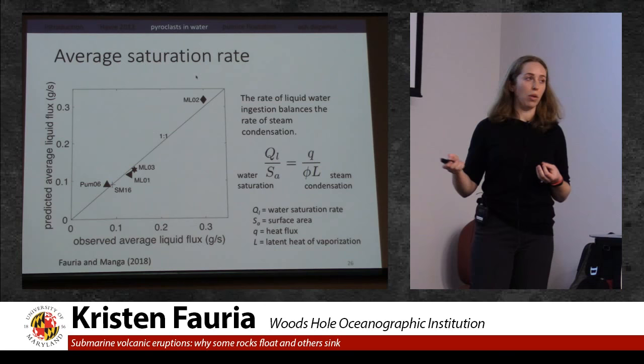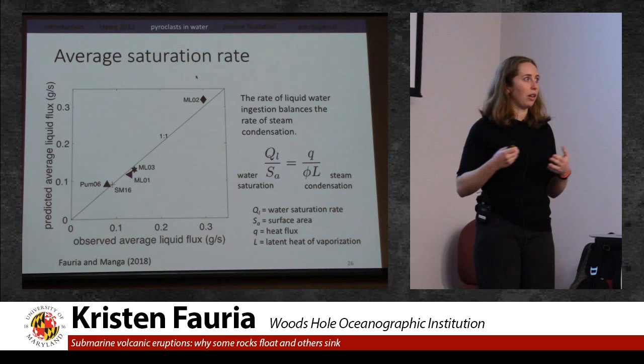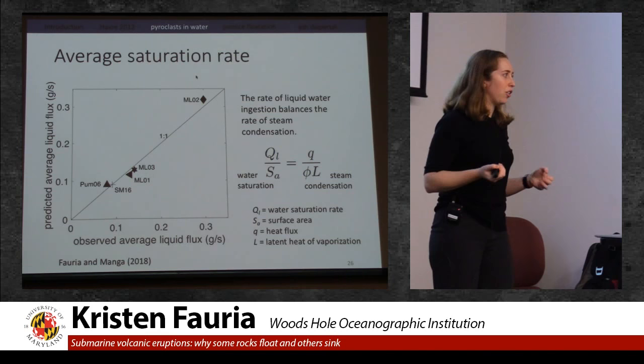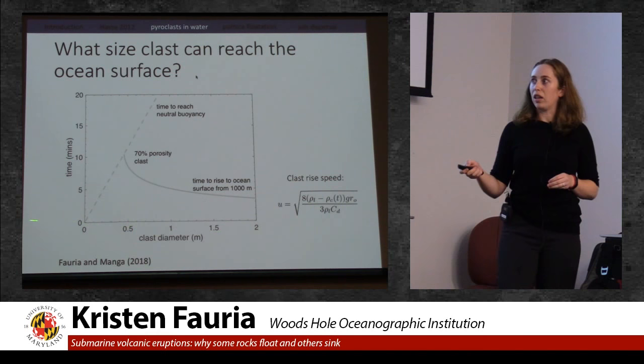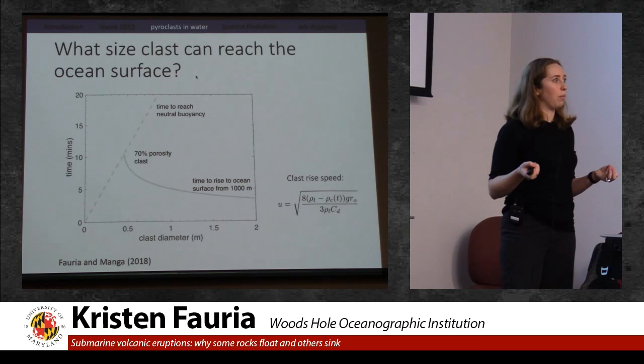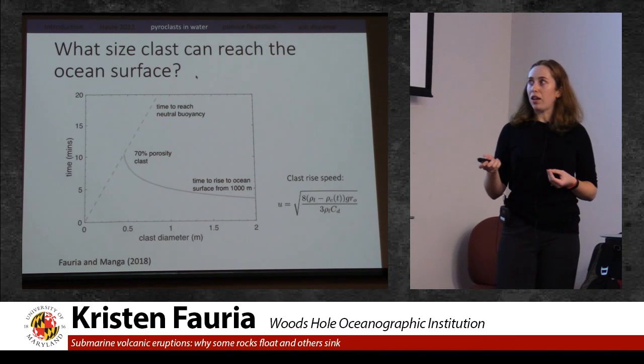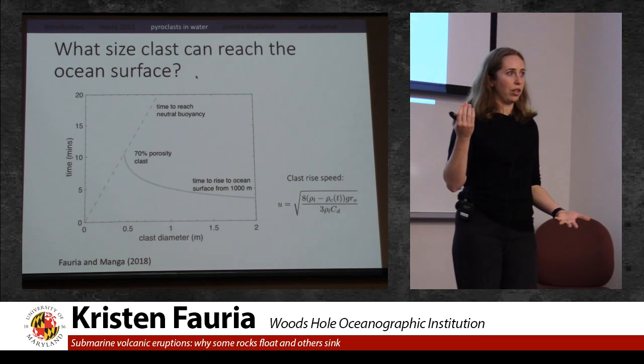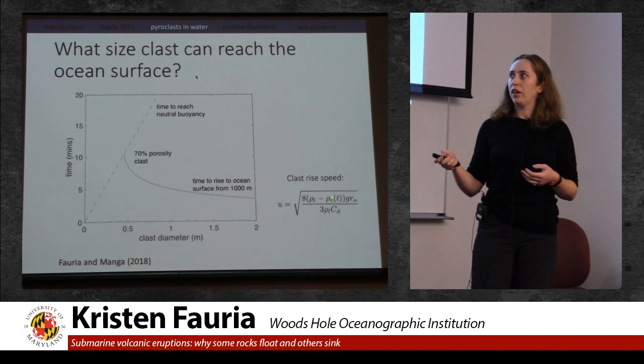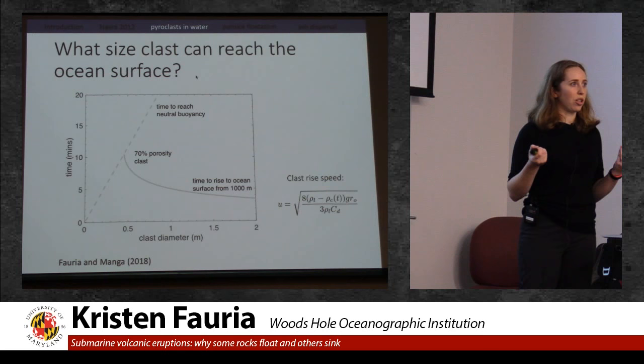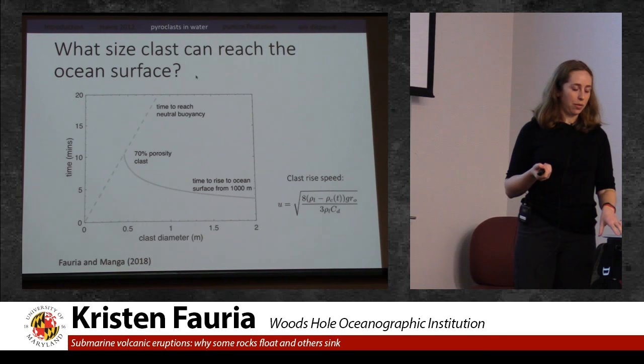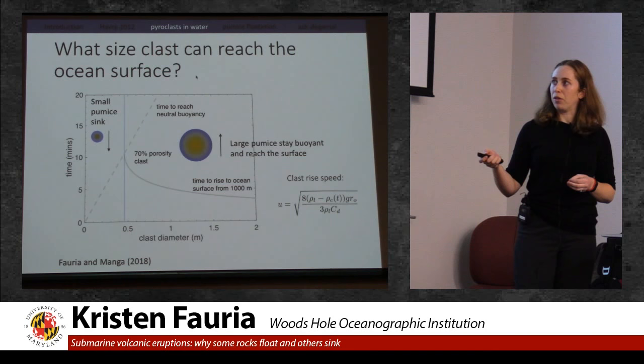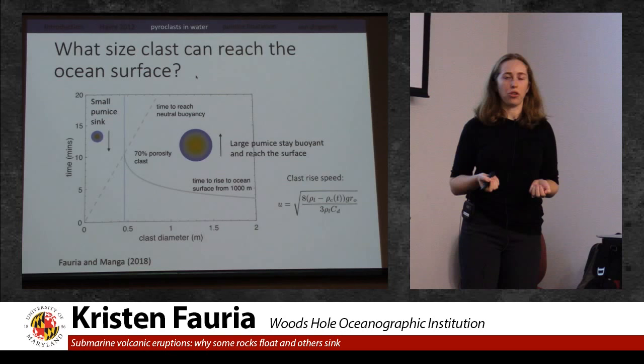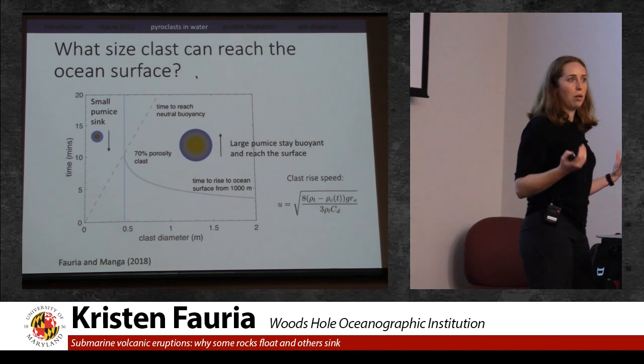So if we use this model then to predict the rate that liquid water is going into the clast, we can calculate how its buoyancy is changing through time. And so here, what I'm showing is the size of the clast versus the time in minutes. The dashed line represents the time when the pumice reaches a point of neutral buoyancy due to saturation. And the solid line is the time that clast will take to rise to the ocean surface, assuming that its velocity can be calculated by this equation. And its density here is changing due to saturation. And the intercept of these two lines represents the smallest clast that's able to reach the ocean surface from a depth of about 1,000 meters. And so what this means is that anything smaller than about a half meter for a 70% porosity clast is going to cool and saturate too quickly to reach the ocean surface, whereas anything bigger than about a half meter is able to stay hot and buoyant and eventually reach the ocean surface before it becomes negatively buoyant.